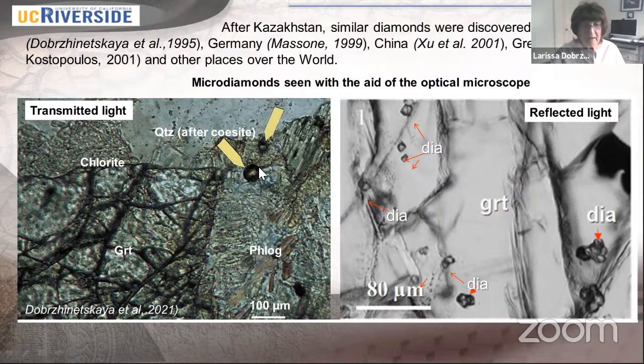And you see here at the grain boundary something very round and non-transparent and actually isotropic, because diamond has a cubic structure. What else is isotropic in this mineralogical setup? Garnet, right? Garnet is also isotropic. So you see something isotropic, then okay, it's probably diamond. Yes, this is diamond, but you have to confirm it by different techniques, okay? So this diamond is sitting on the grain boundaries. It's a very important observation, because later it will help us build a concept of the origin of this diamond. So this is another crystal of diamond.